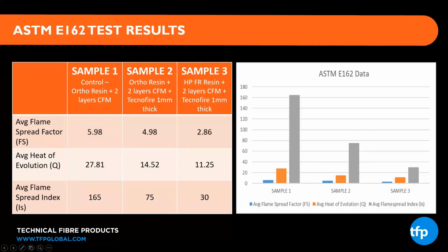I won't break down every number, but you can see as we've gone from the single control through to a full systems approach, we've reduced that flame spread factor significantly. The average heat of evolution as well was reduced down almost in half, and then less than that in the systems approach. And the key to this test really is that Is, that flame spread index, which started at 165 for the blank and ended up at only 30. The bar chart on the right just summarizes those 3 different measurements.